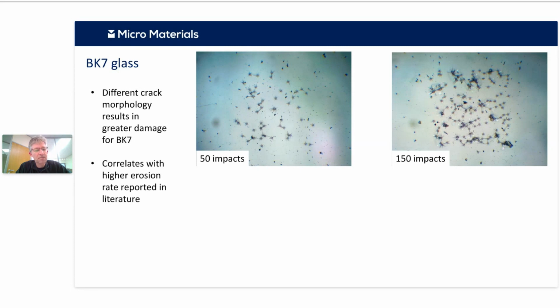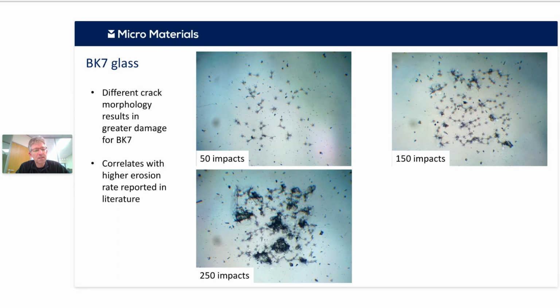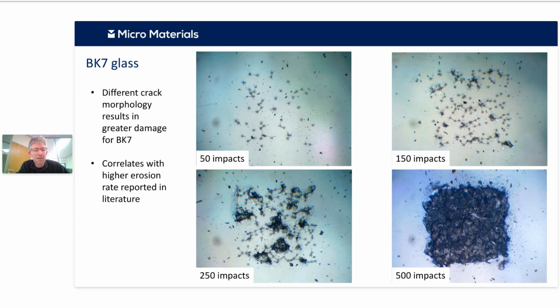And if we run it under exactly the same conditions, we can see by 250 impacts, large amounts of the surface are starting to be totally destroyed. And if we run it on to 500, we can see there that the whole surface is totally destroyed. So very clear, correlates with what you see in the literature for erosion. So we have a very nice